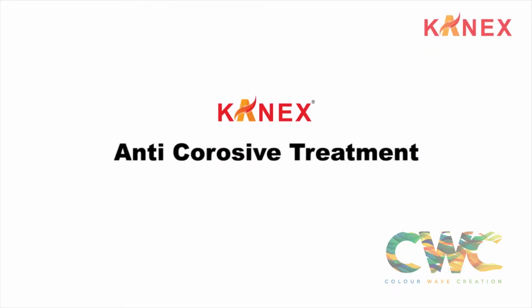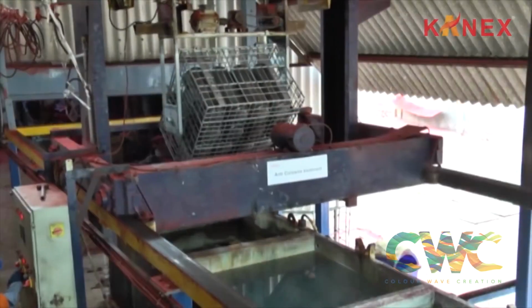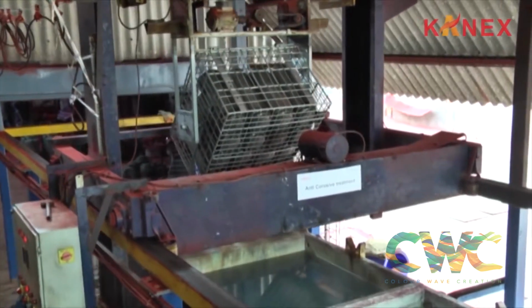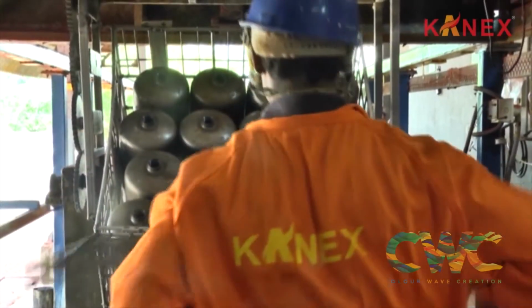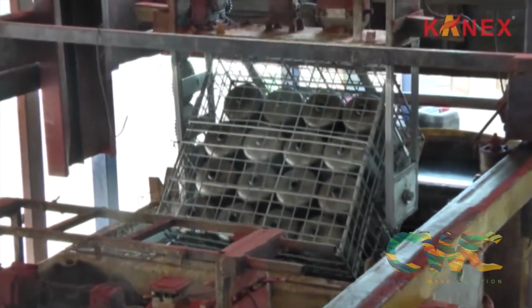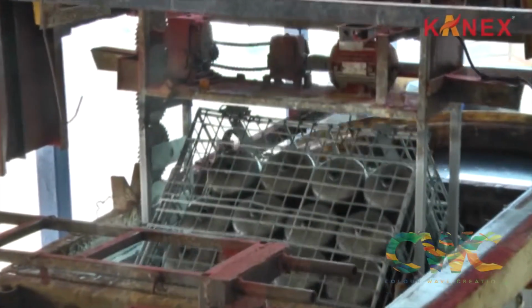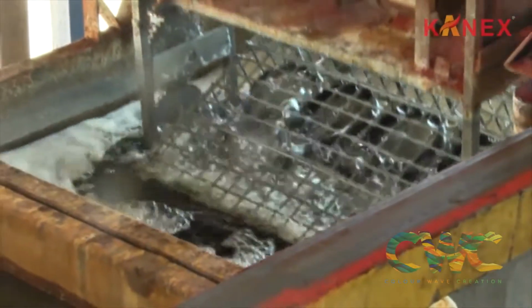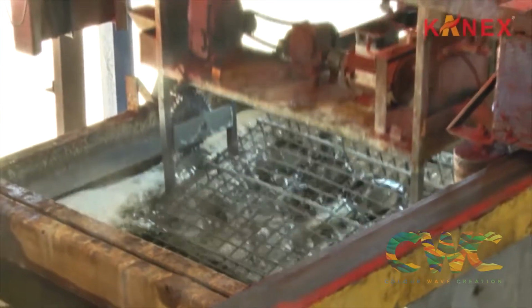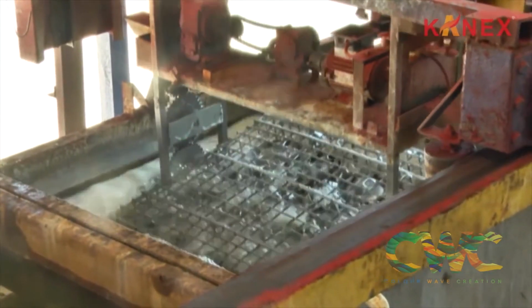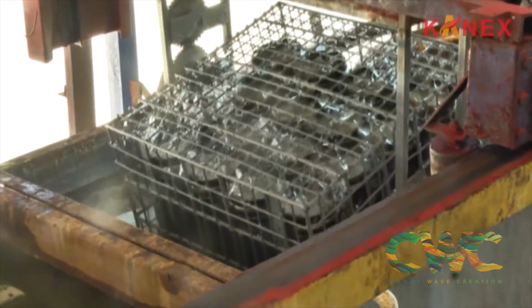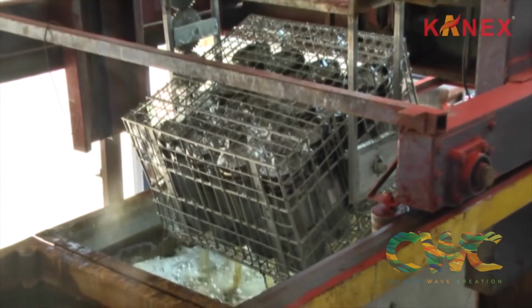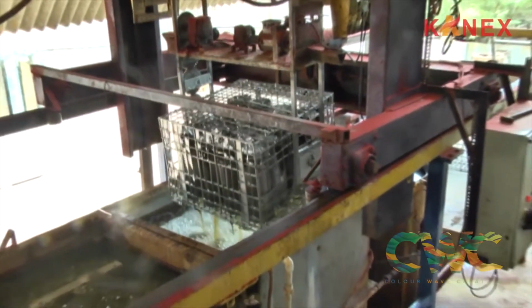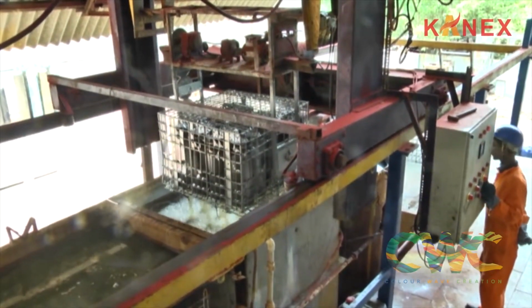Then the cylinders arrive at a semi-automatic anti-corrosive treatment plant that is equipped with an 8-tank phosphate treatment hot process. The cylinders are then loaded in the baskets. These baskets take the cylinders through the different stages like degreasing, derusting, activation, phosphate treatment, passivation, and water tanks for cleaning extra chemicals on the surface of the metal body. This automation process increases the life of the fire extinguishers. Quality control engineers follow the process at each stage.